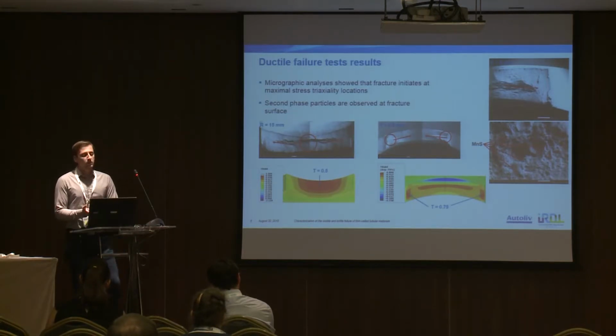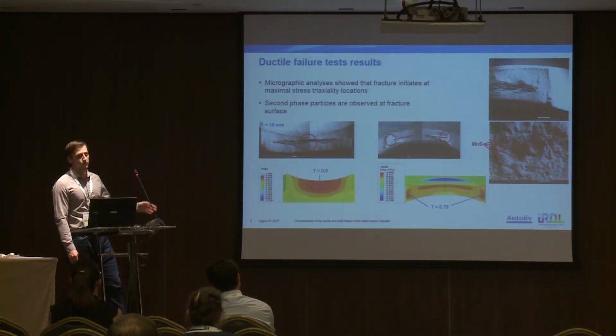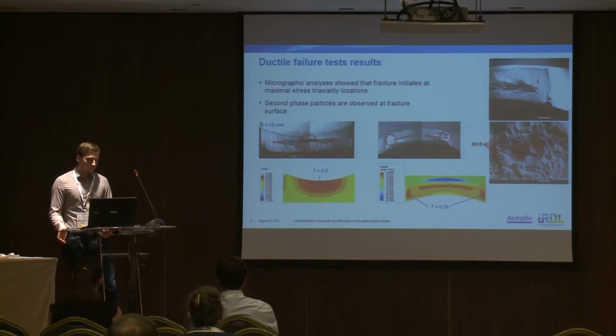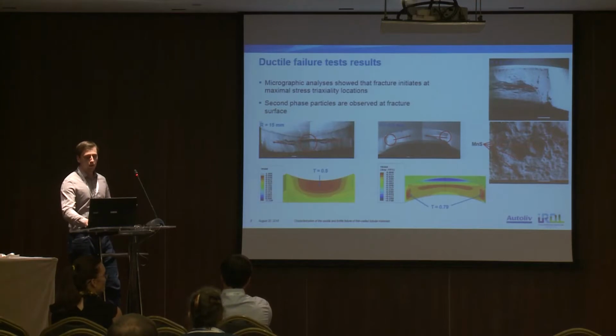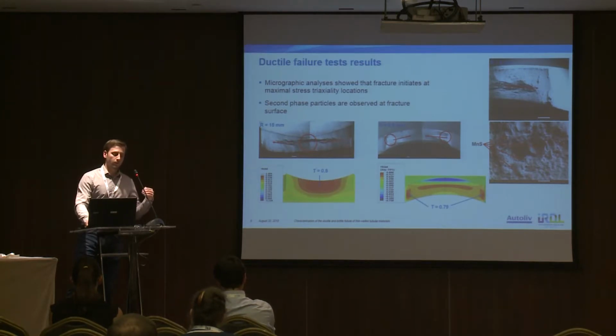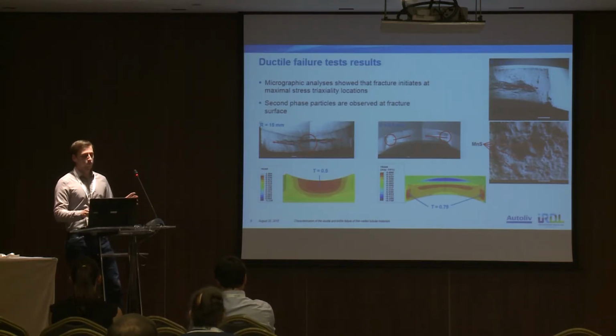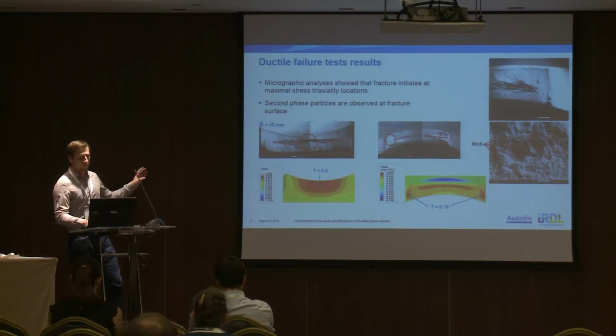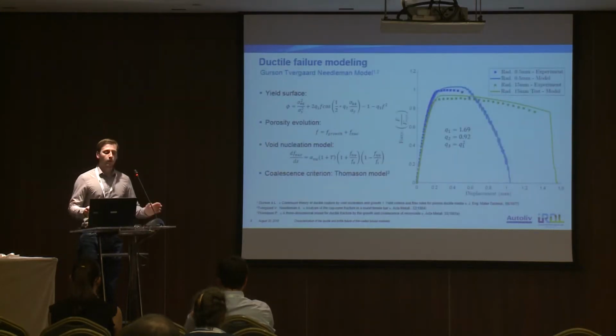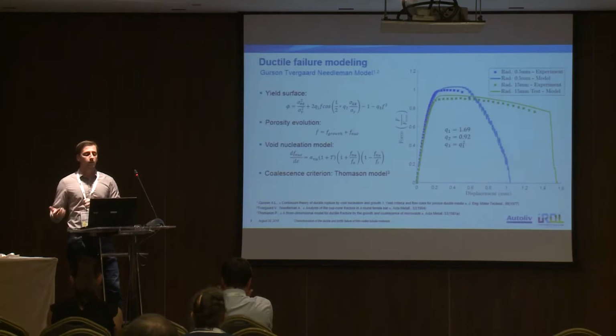Then there is a second point, which is that micrographic analysis showed that fracture initiates at, of course, the maximal stress triaxiality location, in accordance with our numerical simulation. So this is in good agreement with our previous calculation, and will be a significant point. It will be great for us, because with this new kind of curved sample geometry, we had some doubts about the validity of those tests. So as the kinematic of fracture was validated, we can start to identify the ductile failure model.